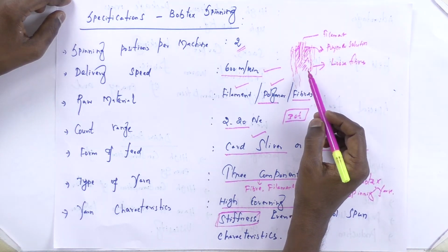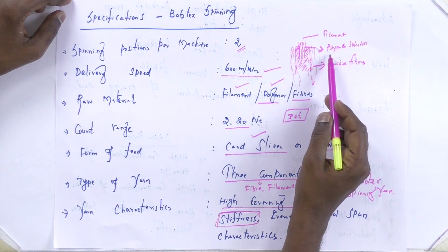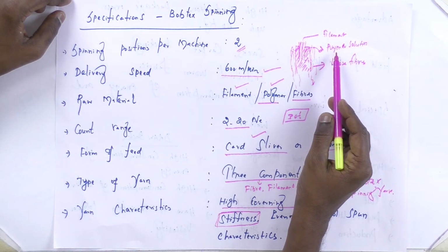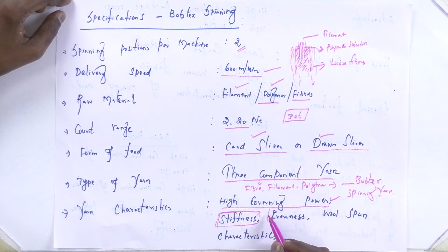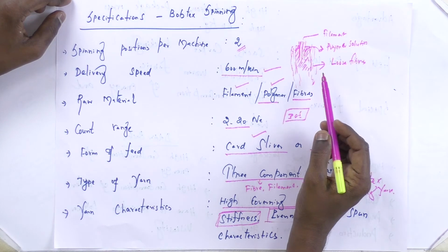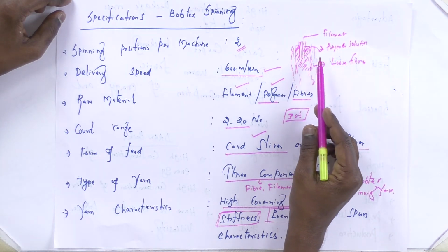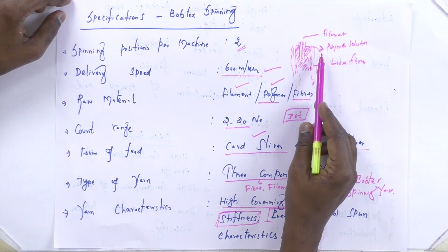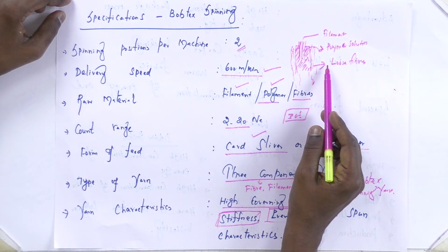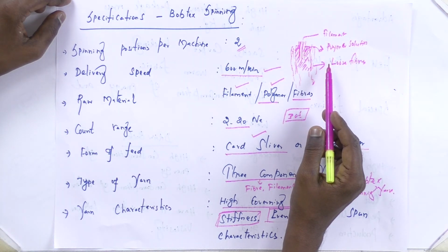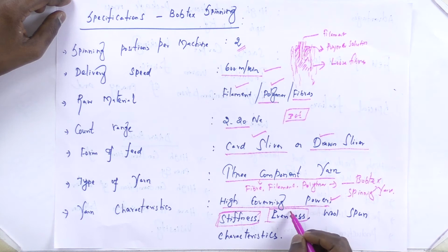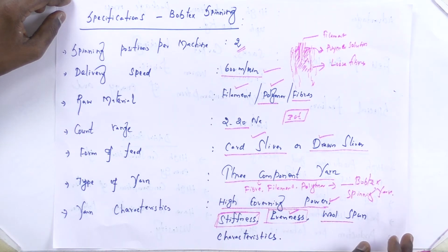we are using the filament yarn with the polymer solution. The polymer is getting solidified, so it gives a very good stiffness effect in the material. The evenness: the uniform filament and polymer make the even yarn. The deposition of surface fiber is also a uniform method, so we can get uniform sliver, uniform yarn, which is known as even yarn. It looks like wool spun technology, wool spun characteristics.